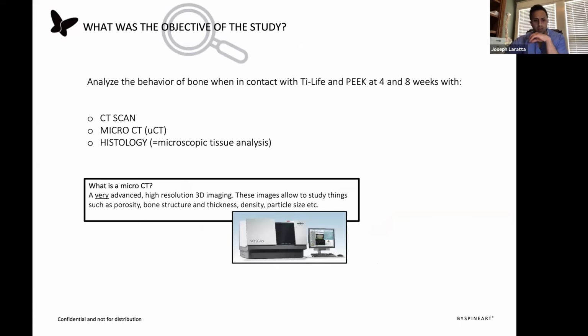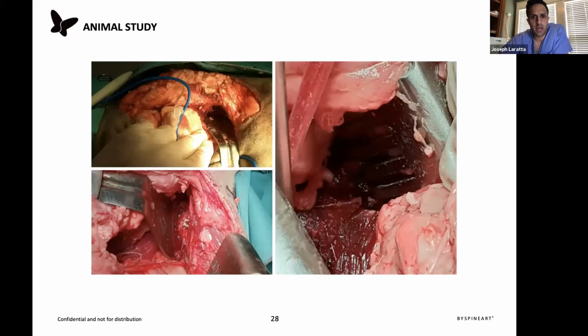And we analyzed the behavior of bone contact with TiLife versus PEEK. We looked at time points 4 and 8 weeks. The literature standard, I think, is 8 and 16 weeks, but we looked at early osseointegration on CT scan, MicroCT, and histology at both of those time points. Unfortunately, the animals underwent sedation, obviously, for their scans at 4 weeks, and one of the animals passed away. So we were left with 7 animals. So even though the study started with 8 sheep, the final results were in 7. So if you see that, that's kind of what happened.